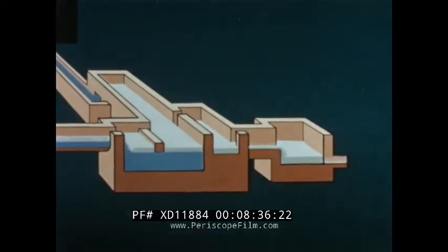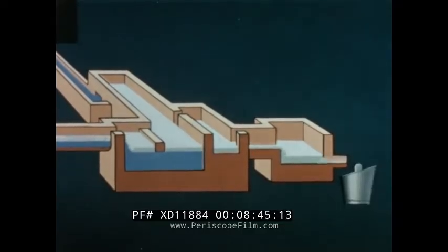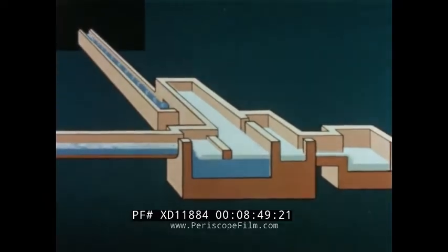This operation takes place in the separation bath, where zinc and lead collect as separate layers. The zinc then runs off into a holding bath, from where it's periodically tapped into a ladle for casting. The molten lead in the bottom layer of the separation bath flows back to the lead splash condenser to be used again.